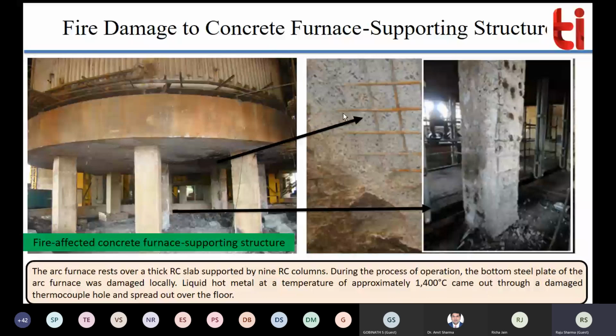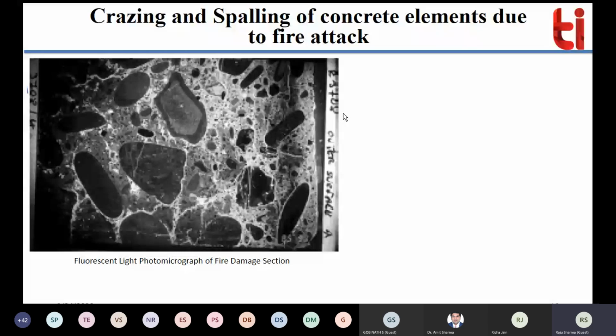In the microstructure analysis, you can see crazing and cracks basically. Through the microstructure you can see the cracks, which you can see in this image also. The cracks are propagating through the aggregate and paste interface, which we call the interfacial transition zone, the weakest zone in the concrete, and the cracks may appear from there and propagate in different directions, right? Your aggregate is also subjected to cracking because of the heat. That kind of extent of damage you can evaluate through microstructure analysis.